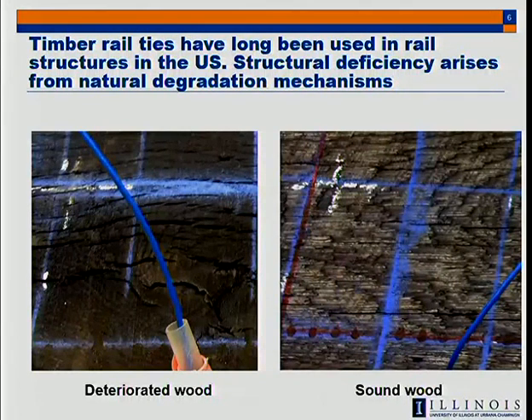And so the principal problem with timber is simply the decomposition of this organic material over time. It rots. And when it rots, it softens and it loses its capacity and it does not maintain the stability of the track anymore. And it's a natural process. It's almost unavoidable. You can treat timber and slow down the process. But if you have moisture and oxygen and environment, the process is going to happen. So we can go from a nice, rigid, stable structure to one that, because of the decomposition that affects its microstructure, is much more compliant.